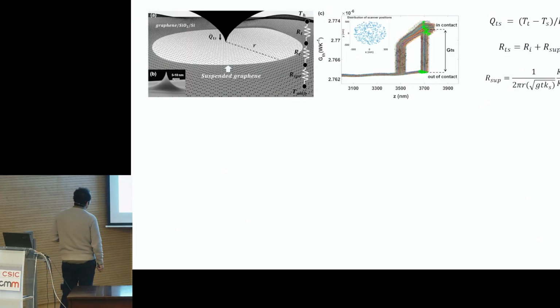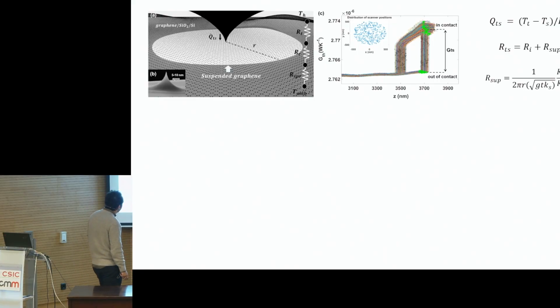So we perform some thermal conductance measurements. We need to take into account several things, but in general, these measurements give us the thermal conductance of the tip-sample thermal contact. You see here the signal that we get when the tip is out of contact, and after that the thermal conductance that we get when the tip is in contact.